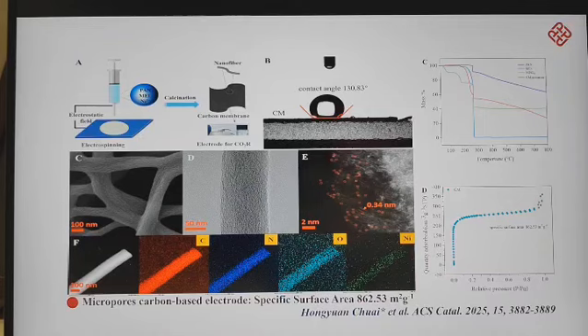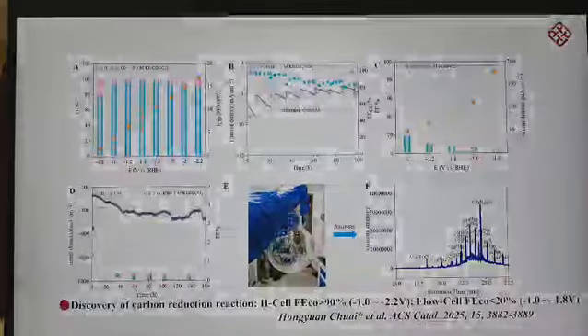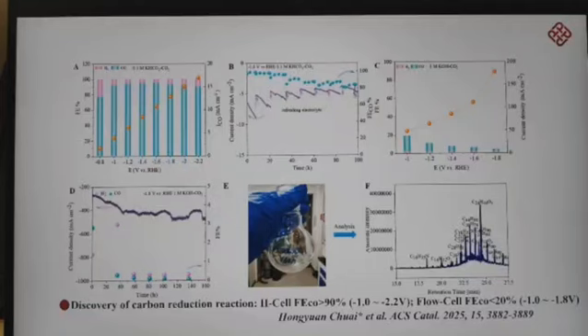We tested the performance of this electrode in an H-cell. The electrode maintained a CO Faradaic efficiency of more than 90% over a potential range of -1 to -2.2 volts, and showed a CO Faradaic efficiency of more than 80% during a 100-hour stability test, which is better than most reported powder catalysts with metal-nitrogen structures in the literature.